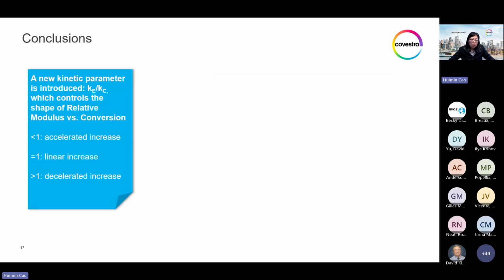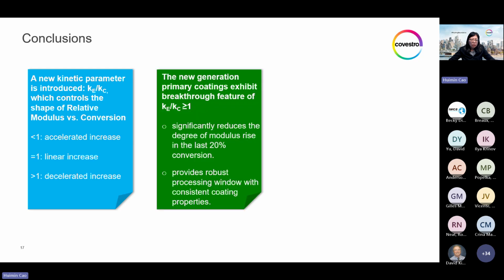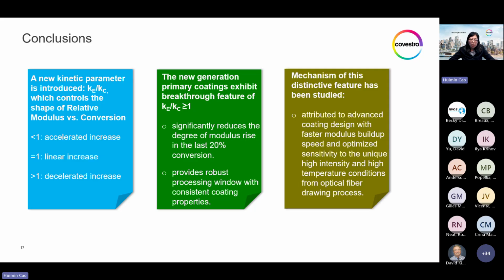So in conclusion, we introduced this new kinetic parameter Ke over Kc, which controls the shape of the relative modulus versus conversion. And we demonstrated our new generation primary coating exhibits the breakthrough feature of a Ke over Kc ratio equal to or higher than 1, which significantly reduces the degree of modulus rise in the last 20% of the conversion. And it provides very robust processing windows with consistent coating properties. And we did some mechanism study. It demonstrated it is attributed to advanced coating design with faster modulus buildup speed and optimized sensitivity to the unique high intensity and high temperature conditions from the optical fiber drawing process.